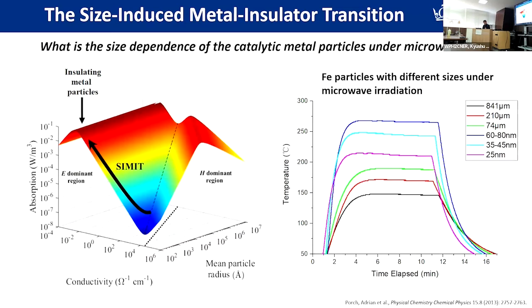The group has done lots of simulations, and the answer is yes. We could choose and control the particle size to see how we could make the metal absorb microwave. Then we did experiments to prove how these different sizes of metal can heat up under the microwave. We chose iron particles, ranging from very small particles, 25 nanometers, up to 841 microns. And we found that with different sizes, the iron particles heat differently in the microwave using the same power input.